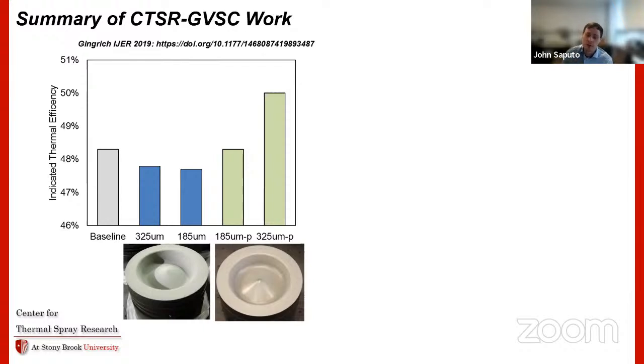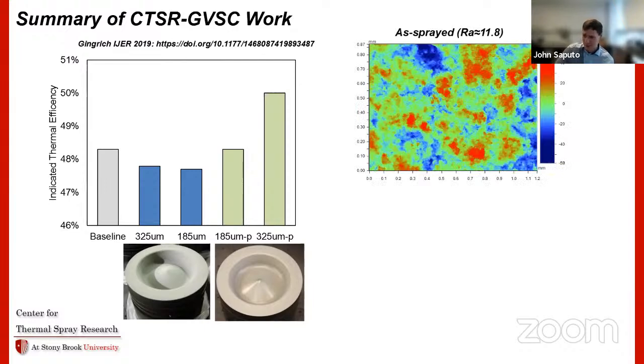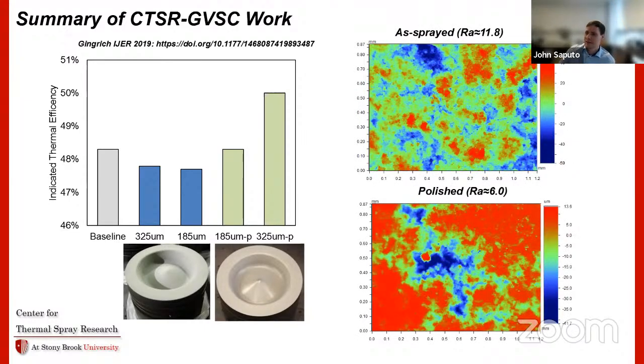All of a sudden you see this performance degradation turn into a performance benefit. And that performance benefit is proportional to the coating thickness. So as you go to that 185 to 325 micron thick coating that's polished on the right, that increment increases, which is good. So we're looking at the surface of these things. It's an as-sprayed roughness of about 12 microns to polished about 6.